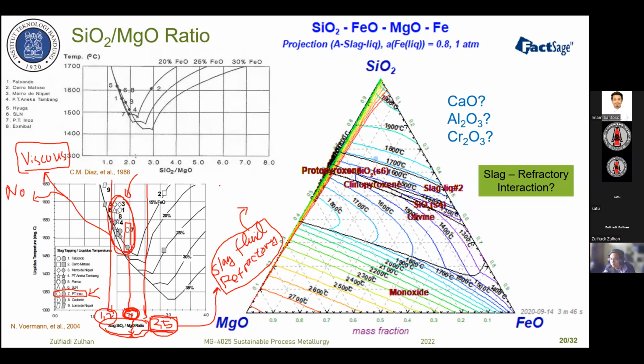if we look now, some plants add limestone to reduce the silica to magnesia ratio or to increase the service life of the refractory. Some plants also add magnesite, MgO. If they have a silica to magnesia ratio around 3, they calculate back how much MgO or magnesite should be added in order to get the silica to magnesia ratio around 1.8.